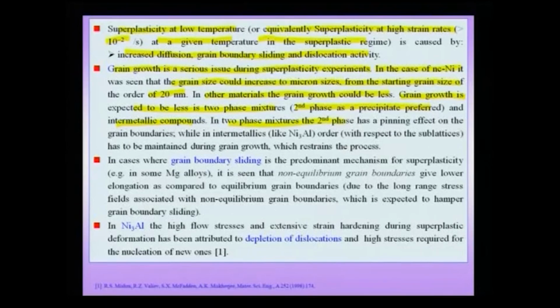In a two phase mixture the second phase has a pinning effect on the grain boundaries, while in intermetallics like Ni3Al the order has to be maintained as the grain growth has to take place. This means that if I really want superplasticity while retaining my grain size, and my final product has to have the same grain size as my initial starting testing sample, then I have to either work with a two phase mixture where the second phase could be a precipitate or a kind of a dispersion which will impede